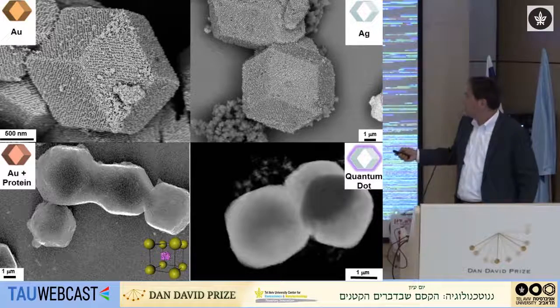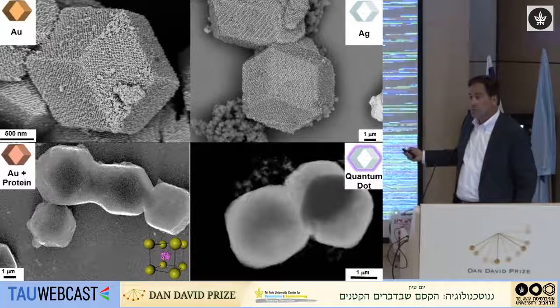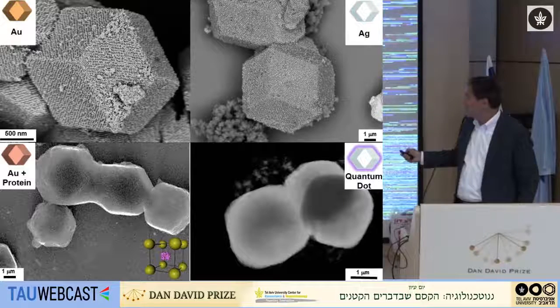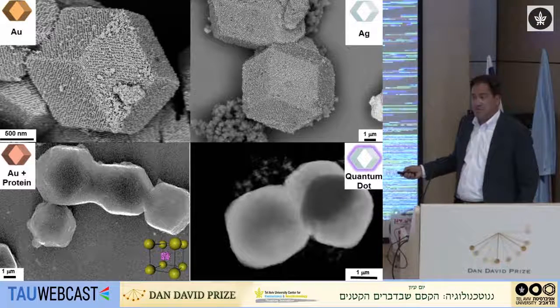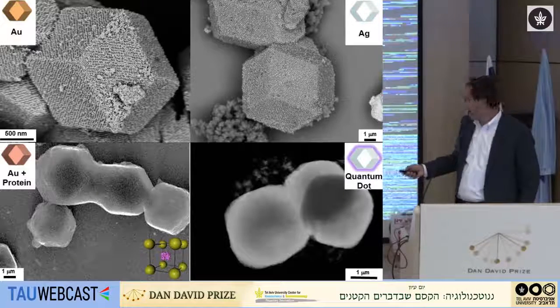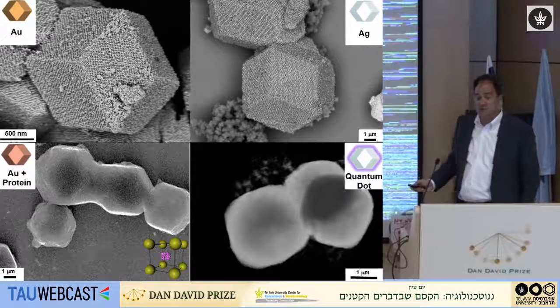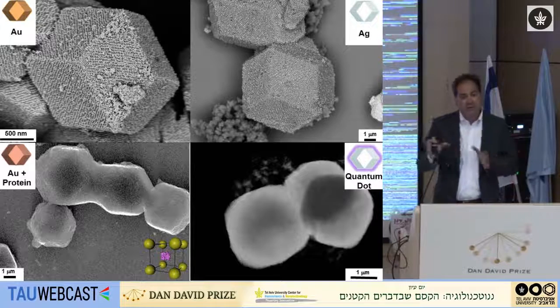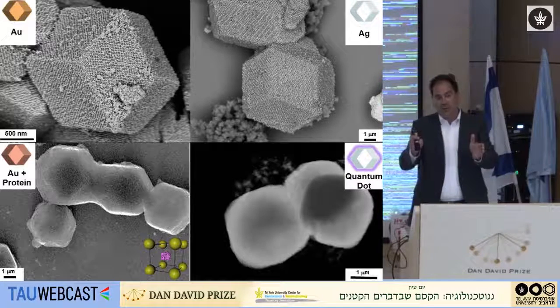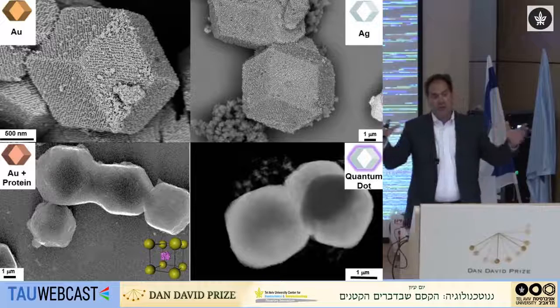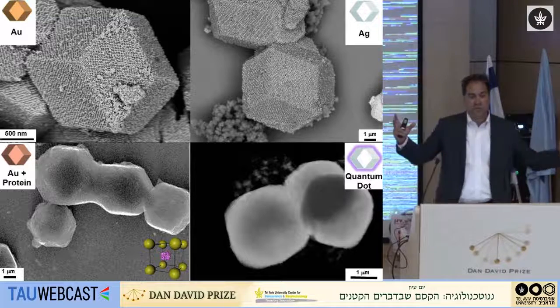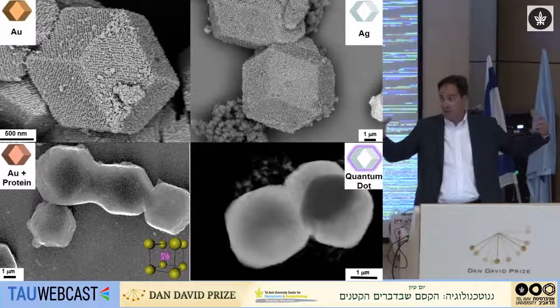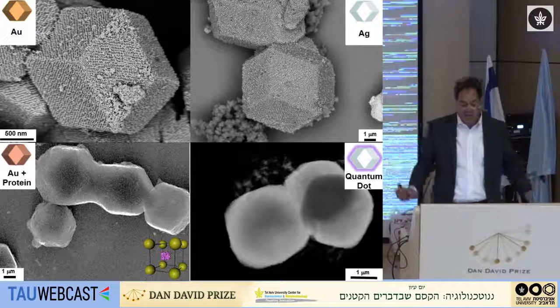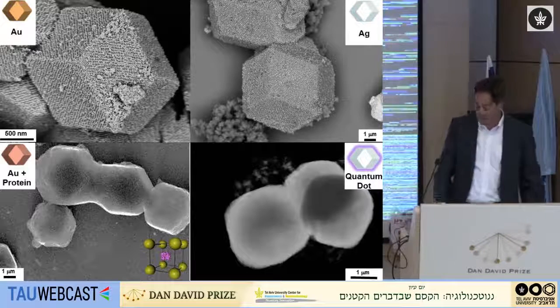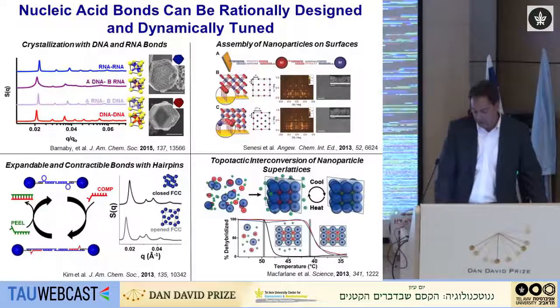So here, this is the gold structure I showed you. Here's silver, rhombic dodecahedral, which is a BCC structure. Here's gold and a protein. This is a catalase structure. This is controlling the crystallization of proteins now. Quantum dot type structures. So the beauty of this is once you have the design rules and once you know how to make a particular structure, if you can turn the particles into a programmable atom equivalent, where again you have oligonucleotides forced upright in the appropriate density, you will drive the system to this particular structure.